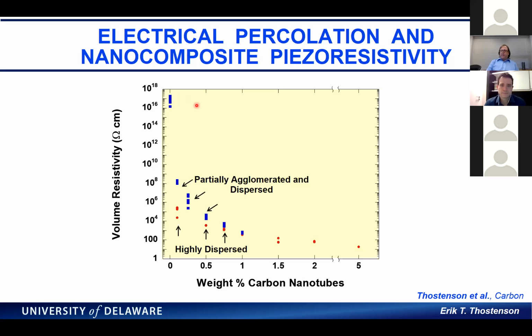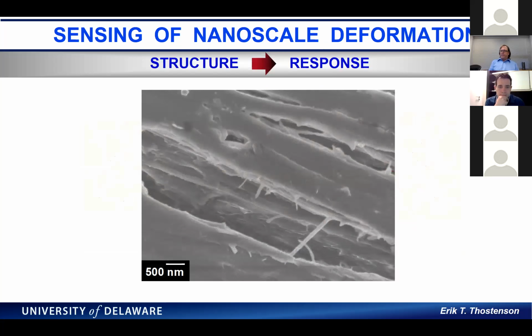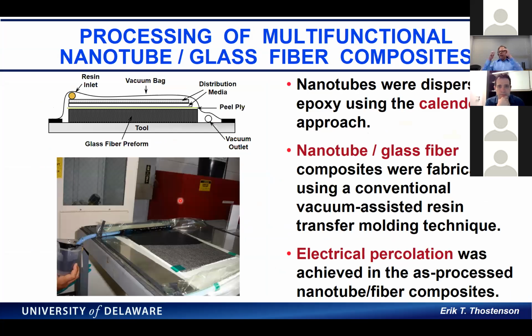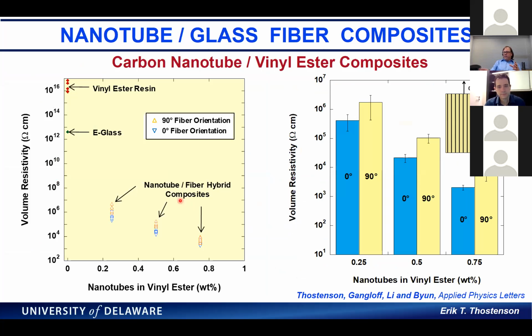Yes. One of the things that we saw, and in fact we published a paper on this in Applied Physics Letters, because every time I would go to a program review, the same guy would ask the same question. We never saw any visible filtration. It depends on your level of dispersion. If you get a really good dispersion, there's no filtration. If you have a lot of agglomerates, those agglomerates actually filter out in the ply if you're doing VARTM, because they can be fairly large. Sometimes we had issues with the dispersion because there was instability, or the chemical functionalization wasn't fully reacted.